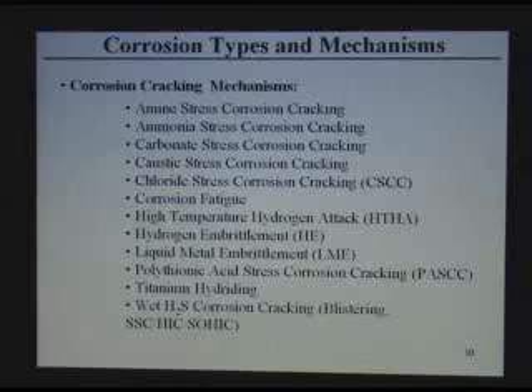Once it goes on, for example, on top of carbon steel, it will crack it right away. They call it liquid metal embrittlement. Polythionic stress corrosion cracking is a mechanism that affects stainless steels and nickel alloys, and it is due to carbide precipitation, and when I go to the slide, I'll explain how it happens.